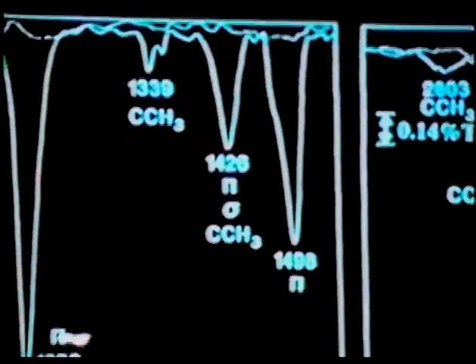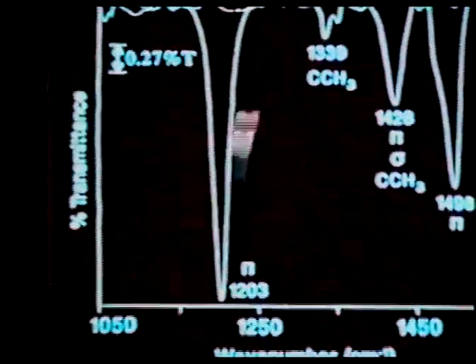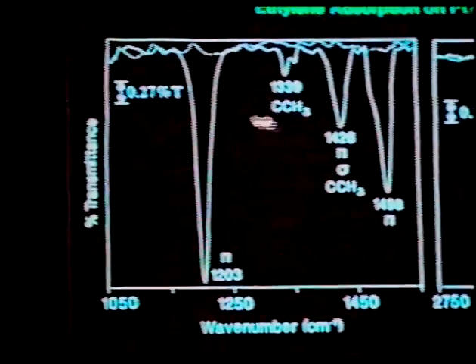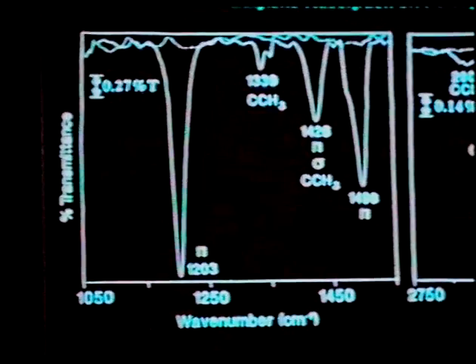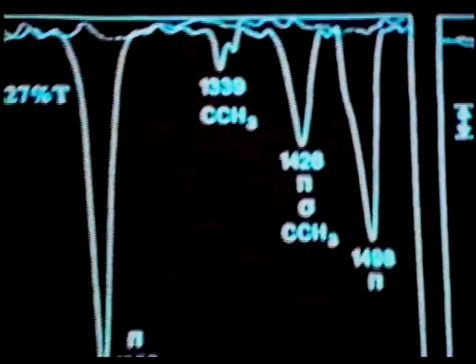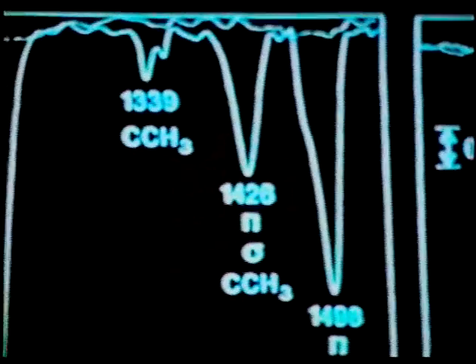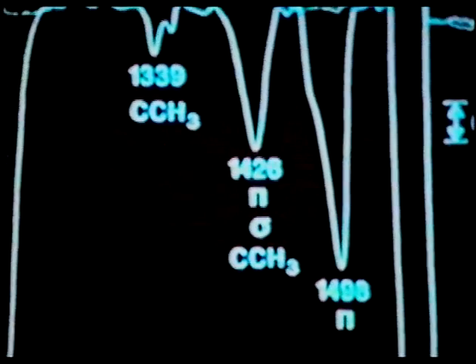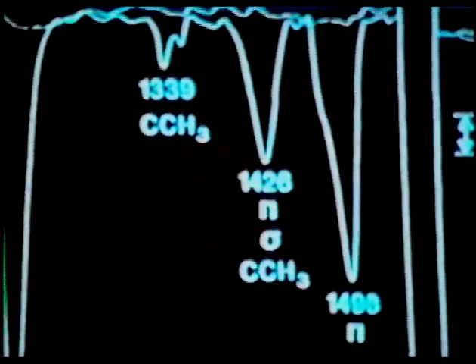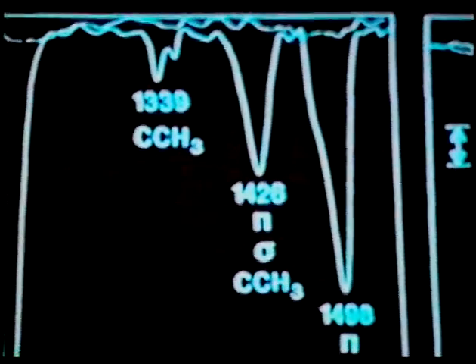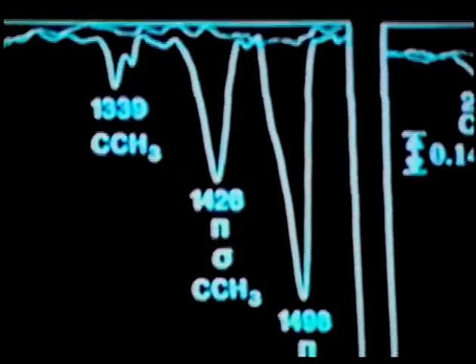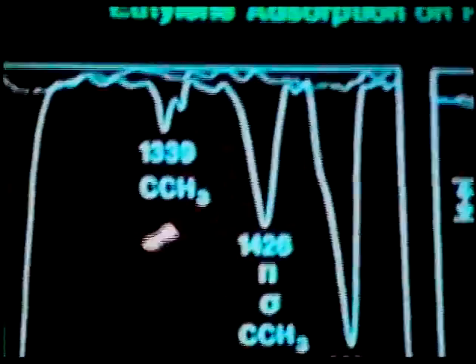What's labeled here is the pi bands. As you can see, it's a very strong band. Here's an ethylidyne band at 1339. This was done at 180 Kelvin. And the reason that we had to go to 180 Kelvin is that if you do the adsorption at room temperature, what you find is only the pi bands or the ethylidyne band. And so what that suggests is that you're going to have conversion of one of these species into the ethylidyne as you warm up. Let me go on further.